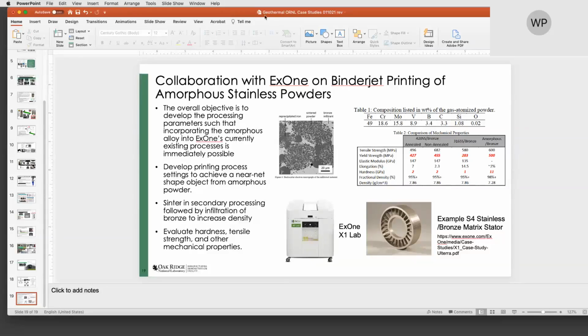So I don't know if you're able to see the slide, but this is an example. You can look at scenarios, and this isn't graded, but look at infiltrate type scenarios. In this case, we used some of those stainless amorphous powders that devitrified. We sintered them such that you had interconnection between those, and then infiltrated it with a bronze material, trying to come up with a very quick methodology to getting wear-resistant parts.